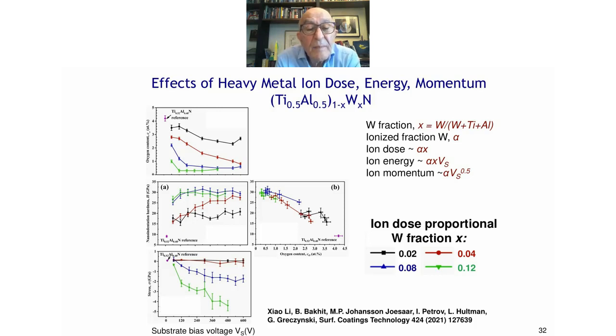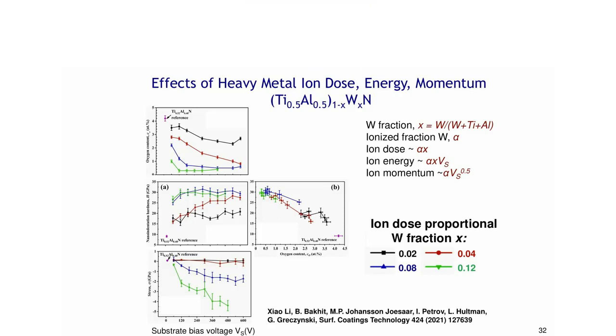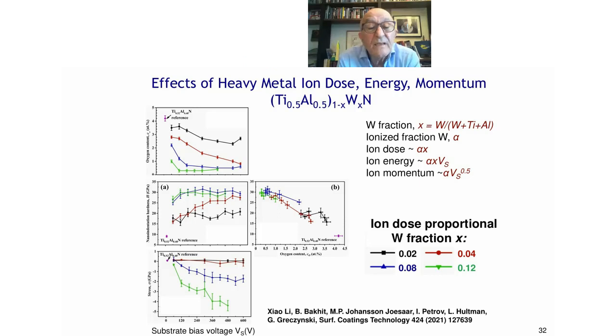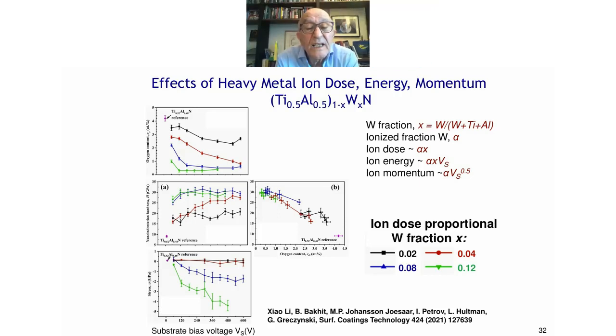Okay, so here now we studied the effect of metal ion dose, again with titanium aluminum nitride, bombarded with tungsten. So what do we mean by ion dose? It is related to the tungsten fraction, X, which is the amount of tungsten in the film as a fraction of the total metal amount. The ionized fraction of tungsten is unknown. It's about, let's say, 50%. But then, the ion dose is half of X.